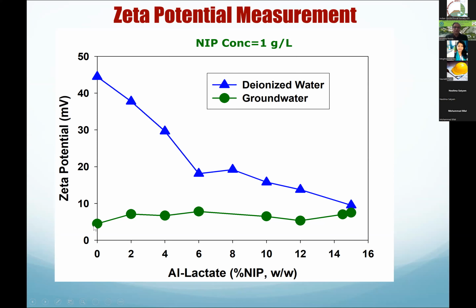But if I use the groundwater from the beginning, with no aluminum lactate, still my zeta potential will go down. And adding the aluminum lactate will not change this one. It keeps the zeta potential much lower. So the whole idea here is that we want the zeta potential to be less positive, so that these nanoparticles can be in suspension. So doing the experiments with deionized water, you actually get the worst results, whereas with the groundwater, which is close to reality, you get a better result. So I suggest, we do that in our lab. We do the deionized water, but we also do the synthetic groundwater to see the effects of the water composition.